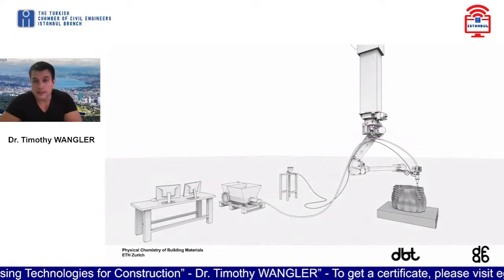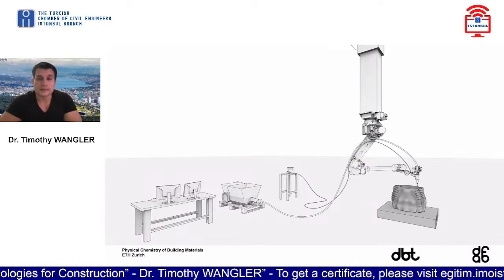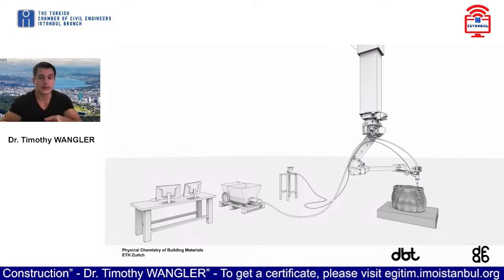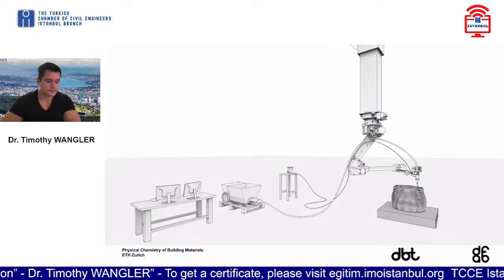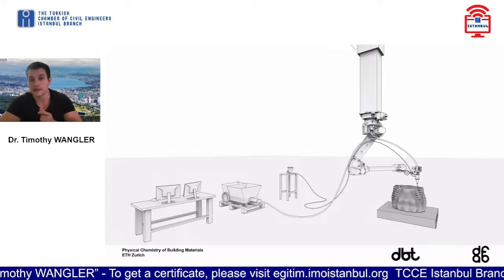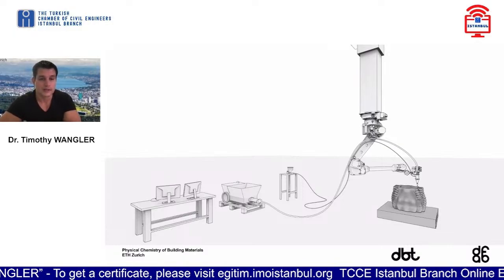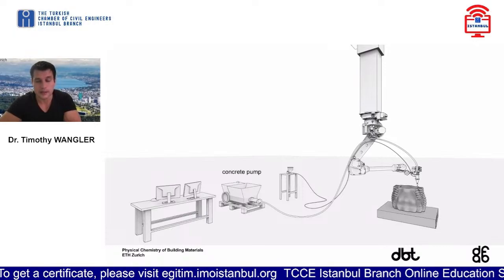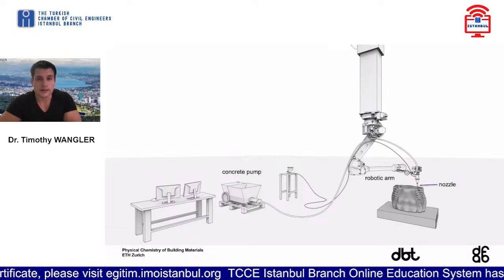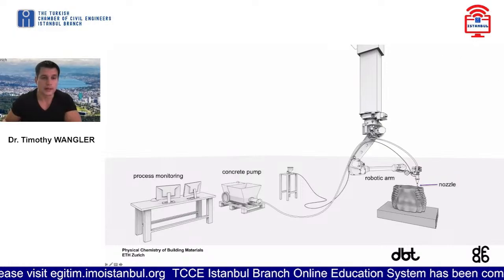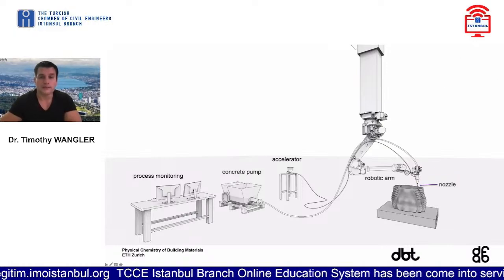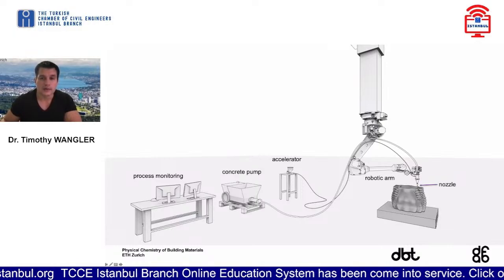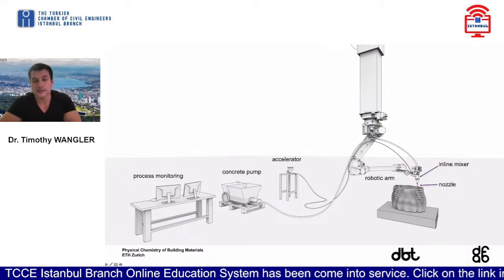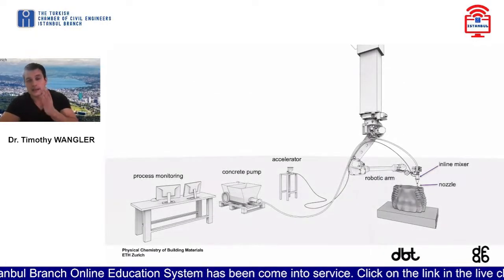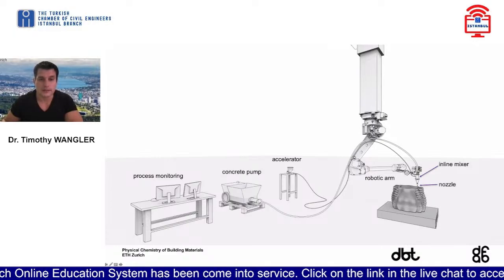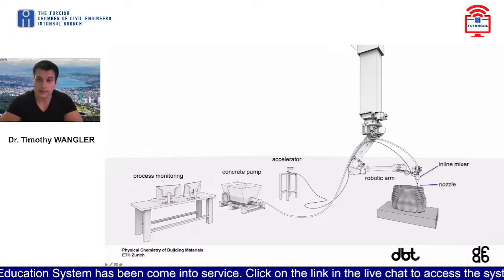Now, accelerators are typically added to concrete right when you mix it in the batch mixer, and then transported to where they need to be transported and then placed. But what we have found in our systems is that you need to add the accelerator as close to the point of placement as possible. So this is a schematic of our 3D printing process where we have a concrete pump. We have our nozzle, so that's where the concrete comes out, and then our robotic arm. So this is our 3D printer because it's all controlled here by a computer, the process. And then we have our accelerator pump, and our accelerator pump is adding accelerator here, right at the point of placement in an inline mixer. And the reason for that is because if you don't add it at the point of placement, then you get buildup normally of accelerated and hardening material in your pumping line, and then eventually your process has to stop.